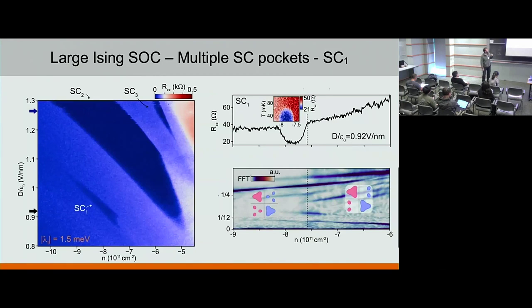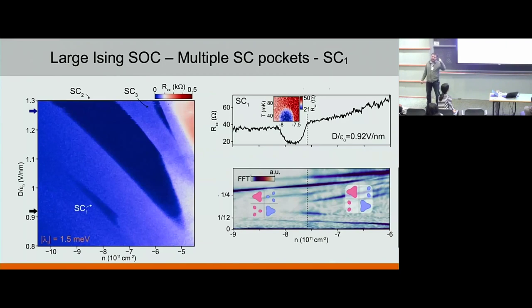But the idea would be that, at least utilizing some of these models, if you think that the density of states is the important driving factor, then you have to take into account that two effects can happen. You either raise the density of states and you get into the superconductivity, or you raise the density of states and then you trigger some phase transition, like a Stoner criterion. And for reasons that are not completely clear to me, or at least I cannot articulate them well, if you increase spin-orbit coupling, you would favor superconductivity or disfavor the Stoner criterion. And in that framework, you can actually obtain that larger spin-orbit coupling will give you larger displacement field. This is how much I can comment, sorry about that.